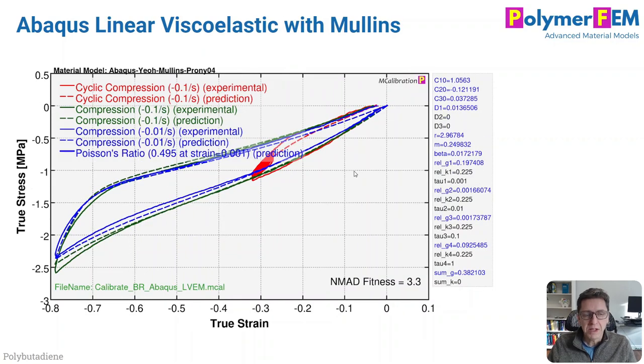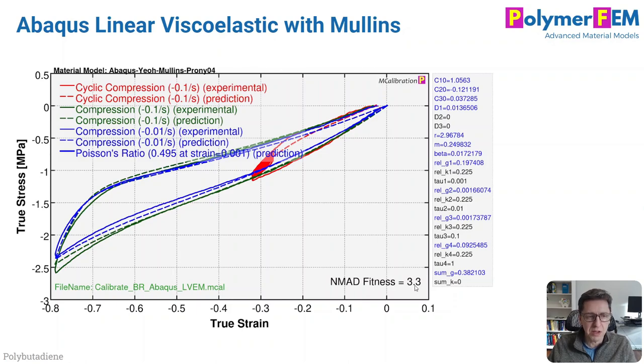What should we do then? Let's try linear viscoelasticity with a Mullins model — we know we need a Mullins model here. We'll see a little bit of strain rate dependence between the dashed lines. Error 3.3%. It's better. This looks pretty decent, actually — perhaps a useful model. But we can do better.